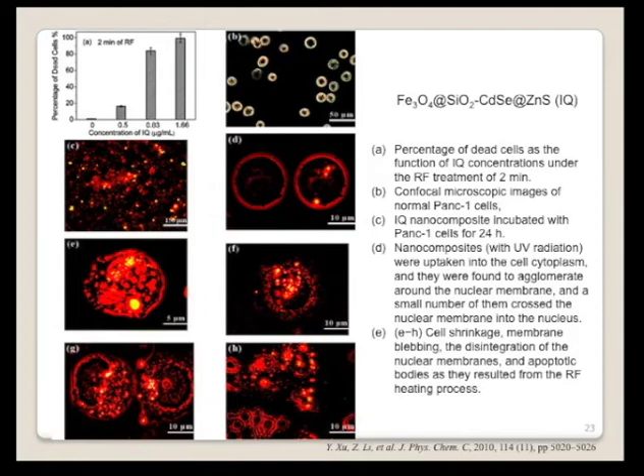We found that if the concentration is above 1.66 microgram per milliliter, almost all pancreatic cells can be killed within just 2 minutes of RF excitation. Right.